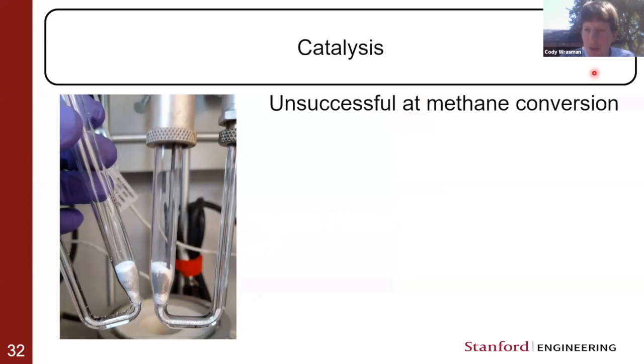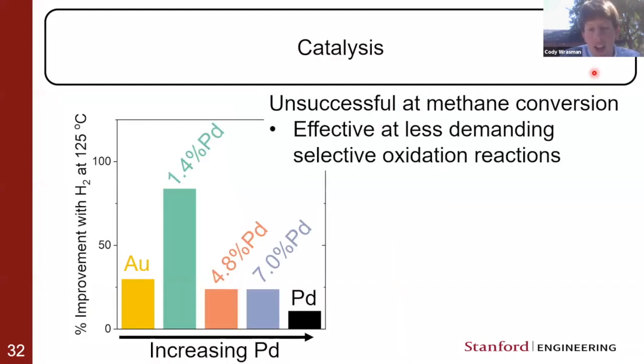As I mentioned at the top, this was the holy grail of catalysis, and it turned out it was actually a very difficult reaction to get to work. We were really only able to make, again, complete combustion catalysts. We weren't really successful at converting methane into methanol. But actually, these catalysts did turn out to be good at less demanding selective oxidation reactions. So this is just an instance of showing the amount of activity that these catalysts had as a function of palladium. And as we expected, or as we hypothesized, the smallest amounts of palladium were actually the best for these catalytic reactions.